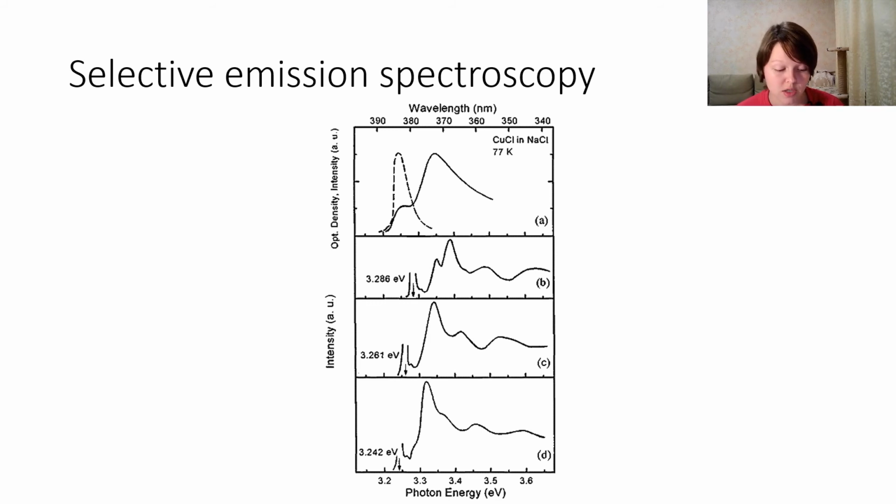Moreover, in case of the weak confinement regime, we can obtain the smallest value of the homogeneous broadening of about 0.1 milli-electron volt, but during strong confinement regime, for very small sizes of nanocrystal, the homogeneous broadening of the spectra will be 10 times more, at least 10 times more.